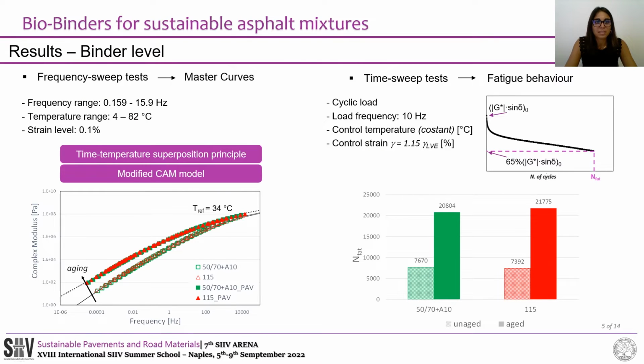From frequency sweep tests, master curves were obtained at the reference temperature of 34 Celsius degrees. The results show that the biobinder and the 115 penetration grade bitumen are perfectly comparable to each other in the entire frequency domain, showing a similar complex modulus trend in both aging conditions.